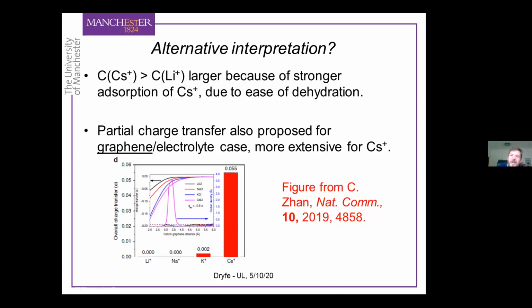But also, this American group concluded that it was a charge transfer, that the larger ions could undergo partial charge transfer from the electrode surface. So what we think of as a capacitance is in fact more like a pseudo-capacitance, because there's a partially Faradaic component to the so-called capacitive behavior that we're seeing. So all this to say that there are specific ion effects, so different ions give different capacitive responses on graphite and graphene surfaces, and I don't think these effects have been studied in a great amount of detail.